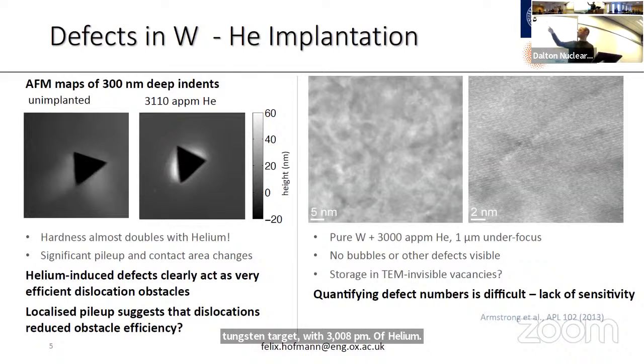And the really interesting thing is you can see that there. Can we turn off these lights so that we can do this a little bit better? Brilliant, thank you. You can see that you have this kind of diffuse contrast in this TEM micrograph, but you can't really pin down any defects. And if you zoom in, we thought there'd be loads of bubbles. Turns out you can't actually pin down any bubbles or any visible defects in this.